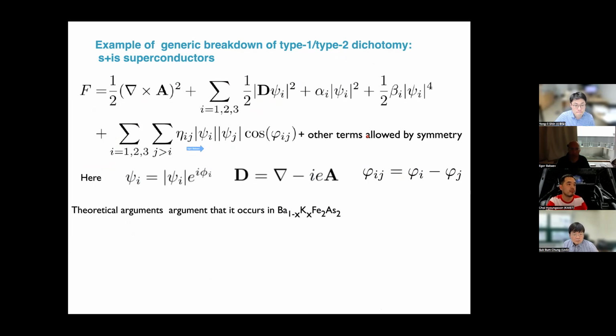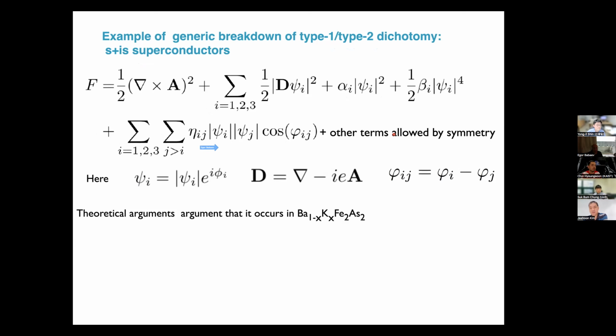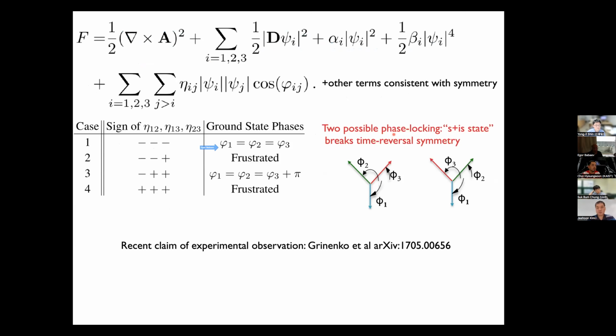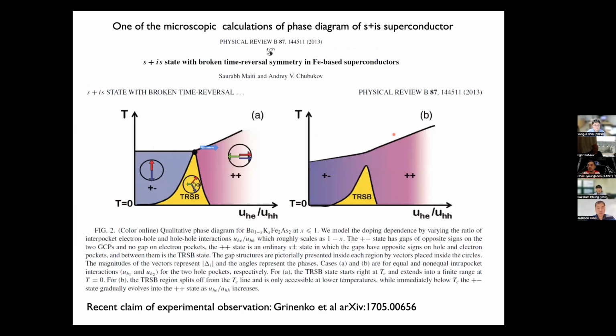Another type of system where the type 1, type 2 dichotomy should be generically broken is S plus IS superconductors. So basically, if you have broken time reversal symmetry of some kind, here you have a U(1) symmetry superconductor as a function of doping, and here you break time reversal symmetry. You also break an extra symmetry on this transition.